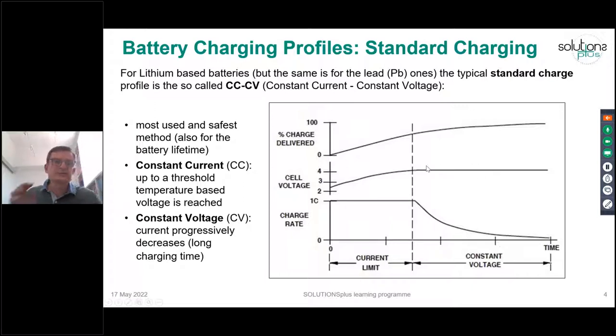As a consequence of this choice, the constant current, constant voltage charge is not as short as we would like, and in particular the second part of the charging, the so-called CV, is, with respect to the state of charge delta we can obtain, longer than the previous one. That can be seen in the upper picture, where the state of charge of the battery is shown over time.